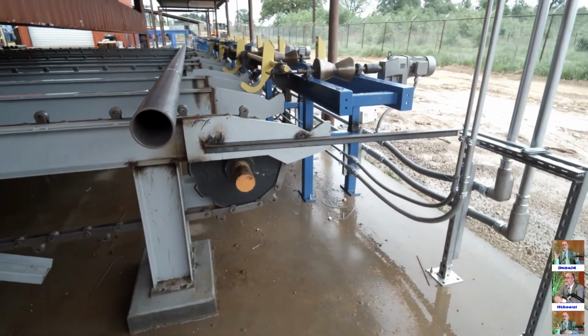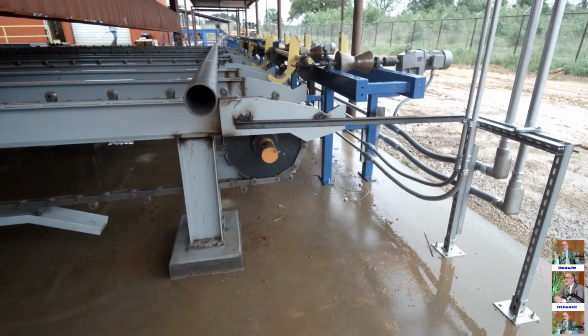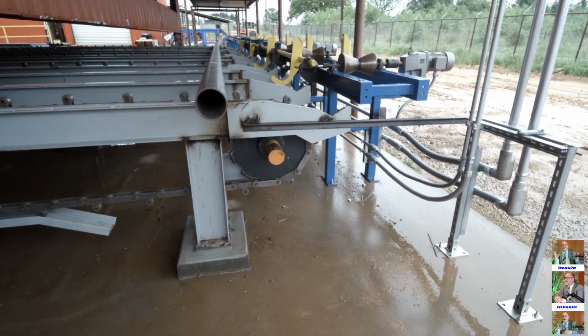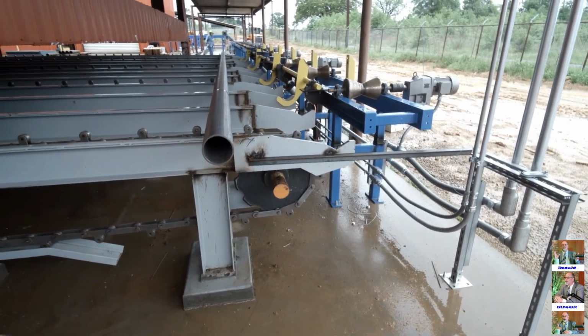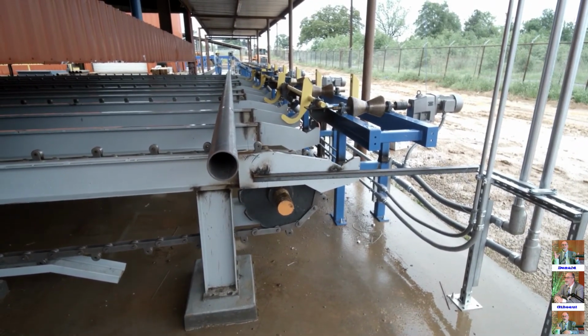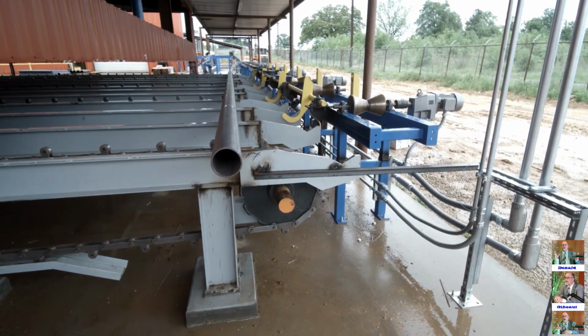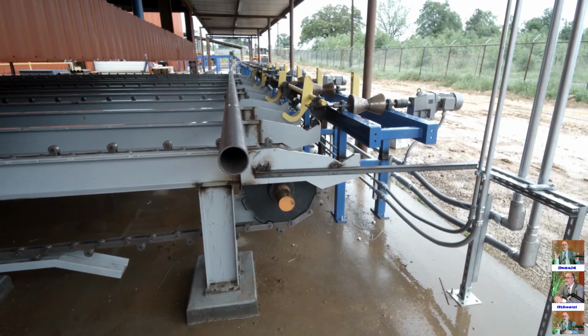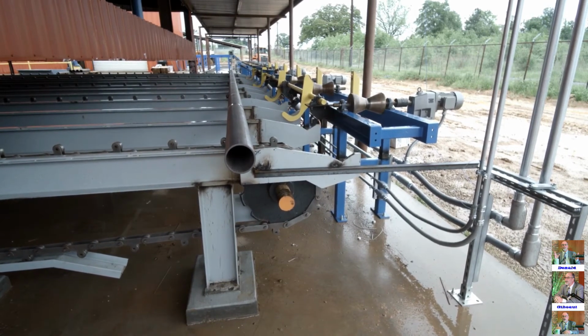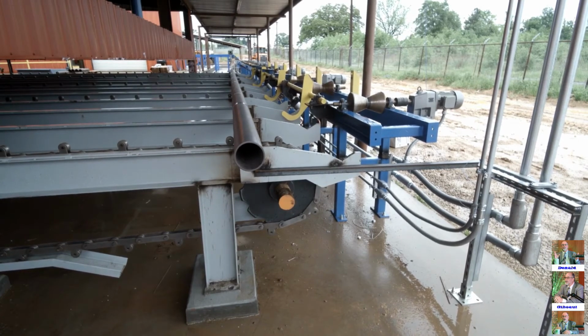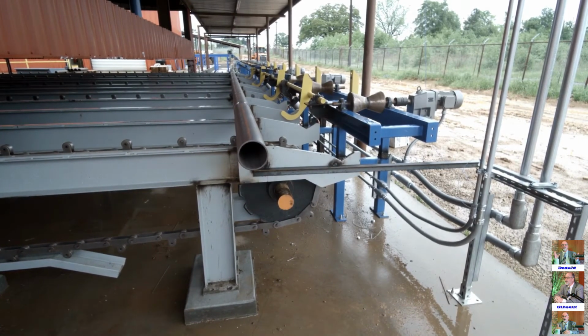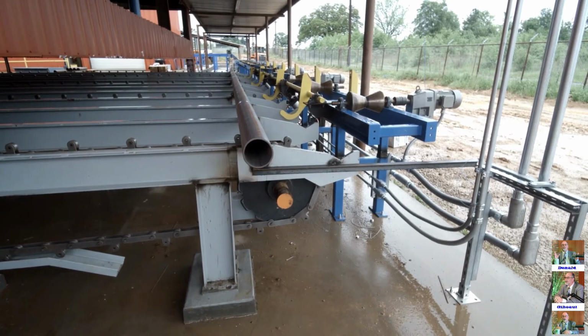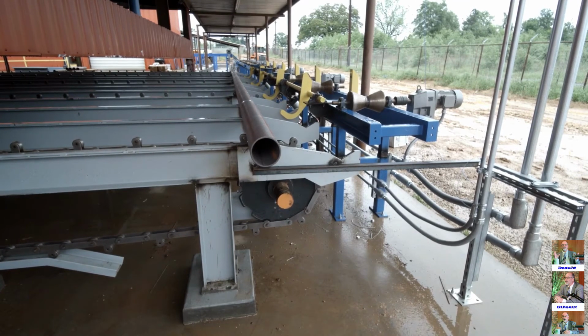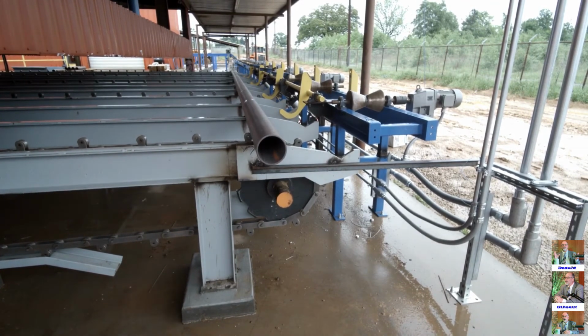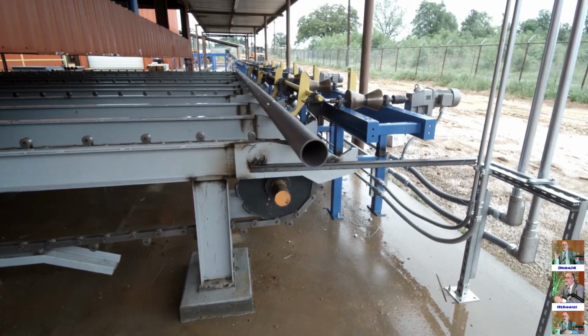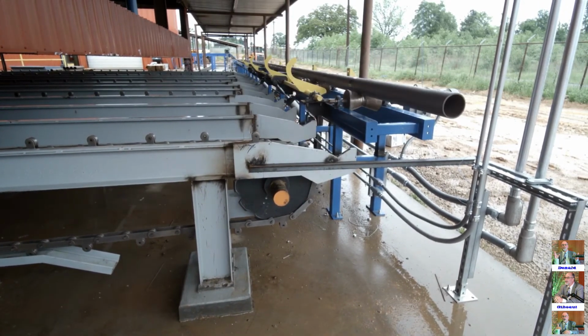As you can see, it rolls. It doesn't keep rolling 100%, but again, it's adequate enough not to get into too much cost. We do have a walking beam on the front end that will fast rotate the pipe, and some people swear by that. But you're talking several $100,000 of additional cost into the cooling bed for that. As you can see here, it just continues to roll. It drops off, gets kicked up onto this exit conveyor.